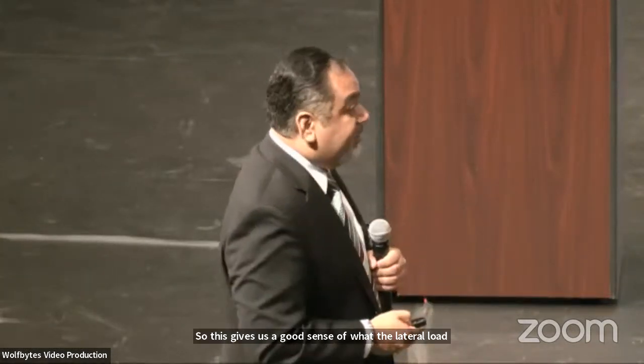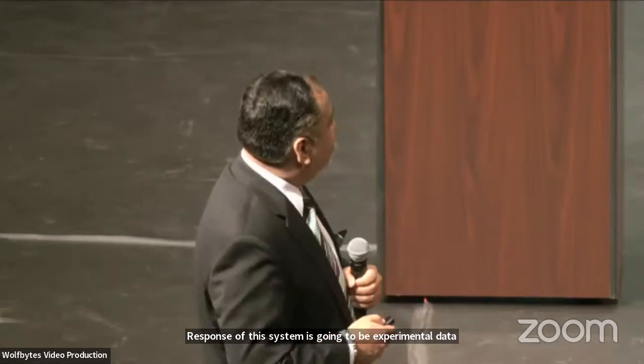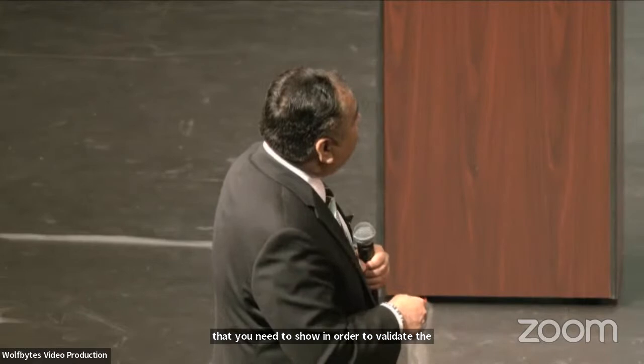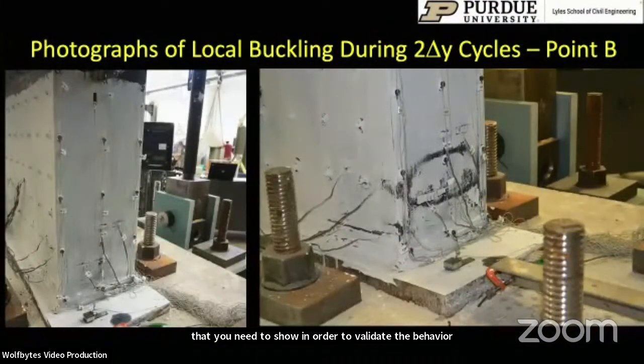So this gives us a good sense of what the lateral load versus displacement response of this system is going to be, experimental data that you need to show in order to validate the behavior of the system. I also have some photographs. For example, these are behavior during the 2 delta Y cycles, and you can see the initiation of compression flange local buckling, which corresponds to point B.